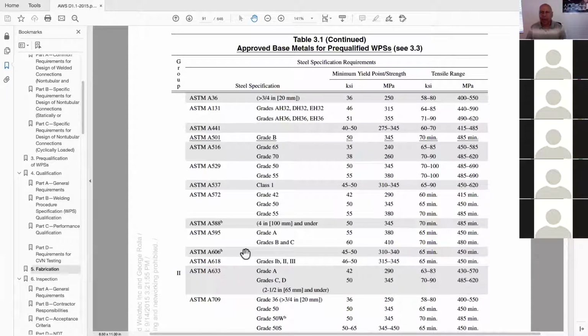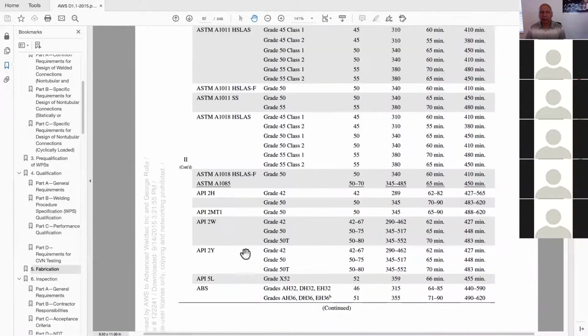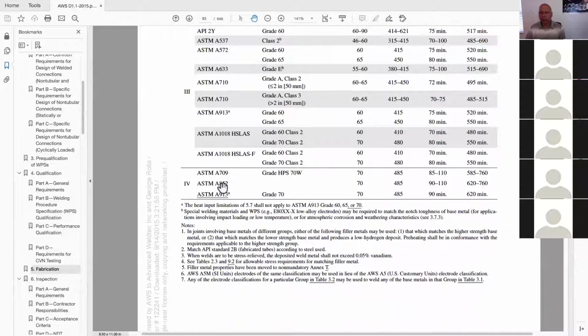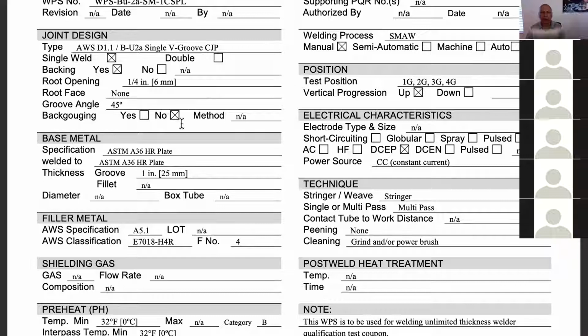That's what we're doing. But it would make no sense to pick a steel like a group 4 steel that has to be welded with a 90,000 tensile strength electrode with a yield of 70 KSI. That would be absurd. You would not get the elongation required for that, and then your test jig would have to have a larger bend radius and so on and so forth. So you get into a whole ball of wax that you don't need to go. You just don't need to go there. When you test a welder, you just simply use a ductile steel like an ASTM A36. Qualify the welder. He's good to go for any steel under that code book.